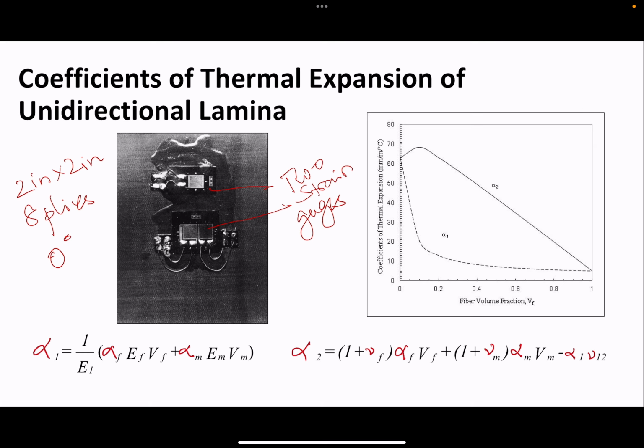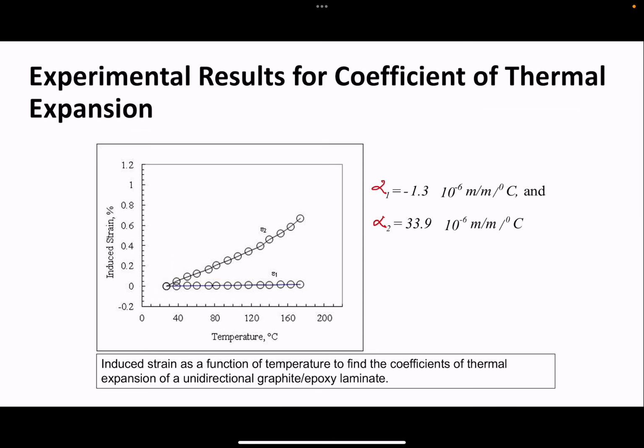And then it's put in an oven. The temperature is slowly increased. The strain is measured by the strain gauges. And then graphs are plotted. On the right hand side, you can see the graphs for alpha 1 and alpha 2. Because it's a composite, of course, the coefficients of thermal expansion, meaning how much your composite expands, is also dependent on the direction in which you're measuring. That's why we are using the 2 strain gauges. So you get alpha 1 and alpha 2, which are of course functions of fiber volume fraction, Young's moduli, and in the second direction, Poisson's ratio. So this is what you draw. You measure the strains and you draw a graph of strain versus temperature.